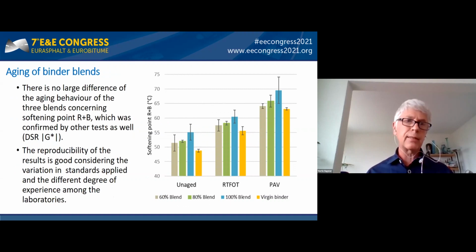If we look at the results of the softening point, ring and ball, where we have more results, I think we have 16 or 17 results. So we also see the scattering better. So actually the precision is quite nice. And what you see is that you cannot distinguish the aging of the 60 or 80% blend from the virgin binder. The pattern is almost exactly the same in the unaged, short-term, and long-term aged stage.